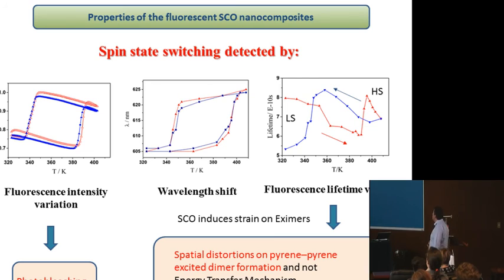So what happened concerning these fluorescence measurements? This is the fluorescence as a function of temperature. You can see that you have fluorescence intensity variation. When you cycle this composite, the fluorescence decreases a little bit. So you have photobleaching, which is well known for organic molecules.